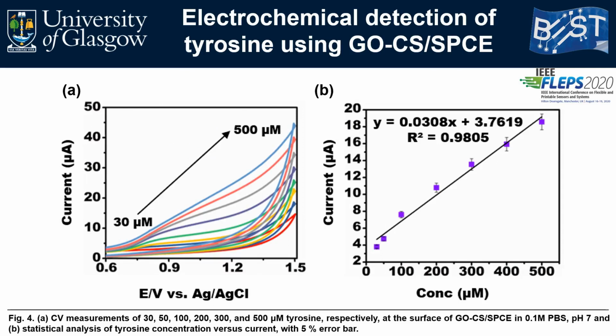Finally, the electrooxidation of tyrosine was examined at the surface of the graphene oxide Chitosan modified screen-printed carbon electrode. Figure 4a shows the CV analysis of 30 to 500 micromolar tyrosine. In the presence of 30 micromolar tyrosine, a prominent oxidation peak was evident at 0.79 volts, similar to the response demonstrated by the graphene oxide Chitosan glassy carbon electrode in the presence of 30 micromolar tyrosine, which shifted to a slightly higher potential of 0.89 volts as the analyte concentration increased.